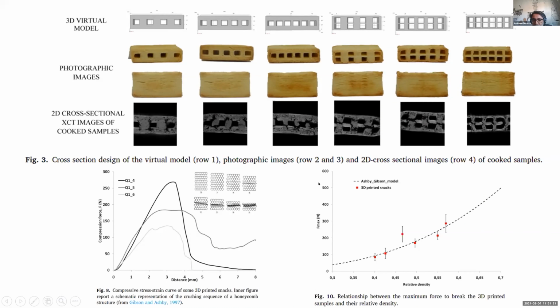This is the relation between the maximum force at this point, the peak force, as a function of relative density. If we are able to fit satisfactorily the max force, the peak before the biscuit is completely destroyed during the texture test, and if the model fits well, we are able to estimate, for instance, if I want a biscuit with a very low F max for elderly people, we have to plan a biscuit with a relative density of 0.35 or 0.3, or also extrapolating, it is possible to obtain some data. So this is a first example, working on programmable food texture.